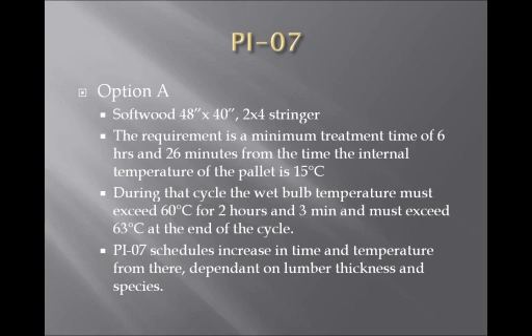During that cycle, the PI-07 calls for you to watch for and monitor both ambient temperatures as well as your wet bulb depression. And your wet bulb actually must meet 60 degrees Celsius, which will start a timer for 2 hours and 3 minutes. At the end of that 2 hours and 3 minutes, it must exceed 63 degrees Celsius. All in all, what it means is within the 6 hours and 26 minutes, you need 2 hours and 3 minutes of wet bulb runtime that is above 60.